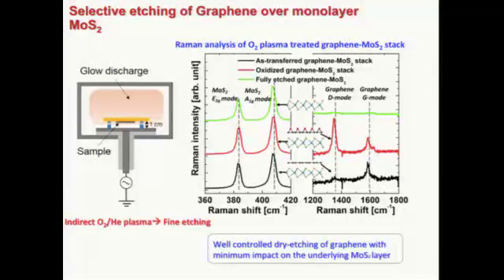So the etching step is very important because that can easily damage the underlying molybdenum disulfide. We want to etch a monolayer of graphene over a monolayer or a few layers of molybdenum disulfide. So we need to be careful with that. Here in this work, we use oxygen plasma with very diluted oxygen. So we dilute it with helium. And then we keep the sample upside down, so it's not directly exposed to oxygen species. And then we also apply just pulses. It's not a continuous exposure.